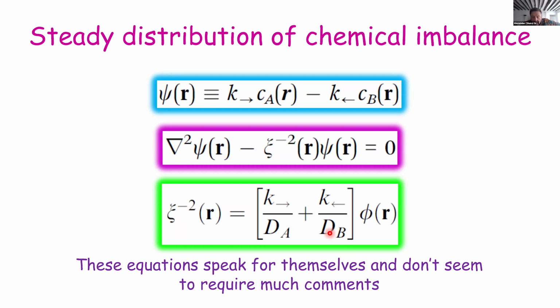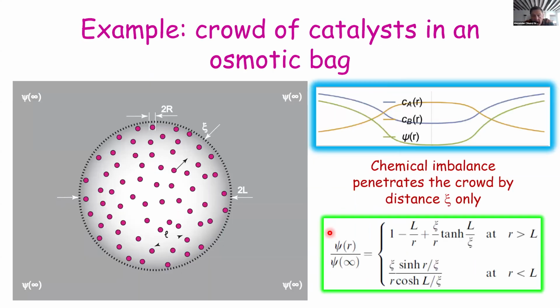Now I want to emphasize that, although there is a 1 over r squared force, which is similar to Coulomb, the nature of this screening is not quite the same as in a Coulomb system, because in a Coulomb system, the nature of screening is closely related to the fact that there are charges of 2 different signs. Here in our system, as long as we have only one type of these catalytic colloids, we have only one type of charges. And so that is the difference. So let's see where it goes.